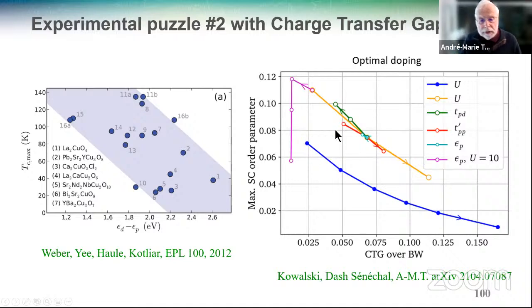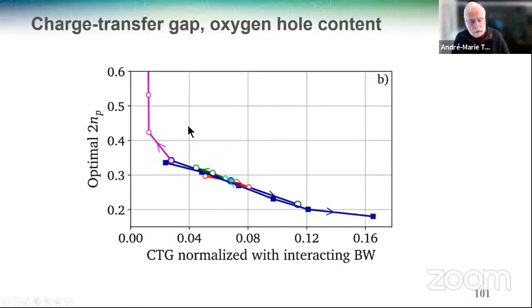So if you plot this, again, the maximum order parameter, but this time as a function of the charge transfer gap in dimensionless units, in other words, as a function of interacting bandwidth, you see now that there's sort of a perfect correlation for the covalent model and for the ionic model. But the ionic model is always lower than the covalent model. So these two facts actually are not independent.